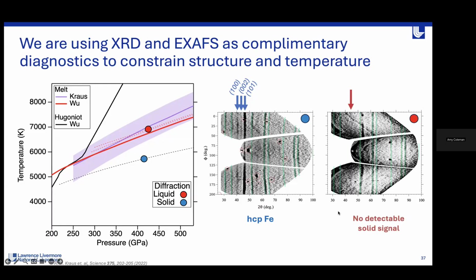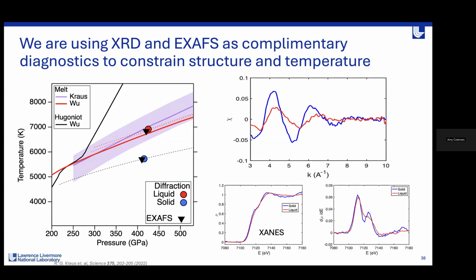So we've got this diffraction data constraining our structure. What we can then do is take the same physics package, use the same laser pulse drive, and probe at the same time - we're basically repeating this experiment, but instead of running diffraction as the primary diagnostic, we can run XAFS.